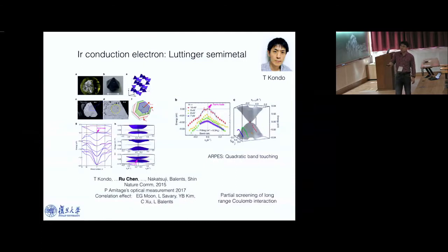But the presence of this quadratic band touching at the gamma point will be preserved. So this is modeled by a so-called Luttinger model, and that's why it's called a Luttinger semimetal. Each band in the system has twofold degeneracy because the system has inversion and time reversal. At high temperature, time reversal is preserved, and inversion is preserved.